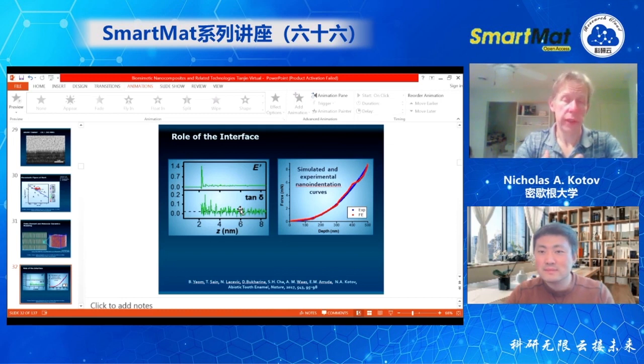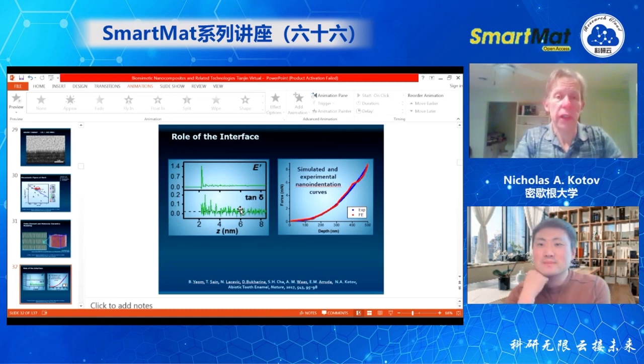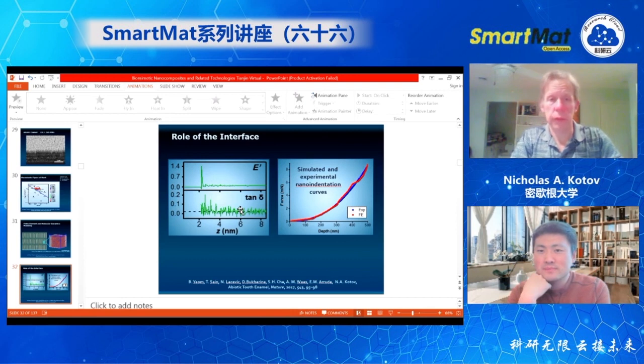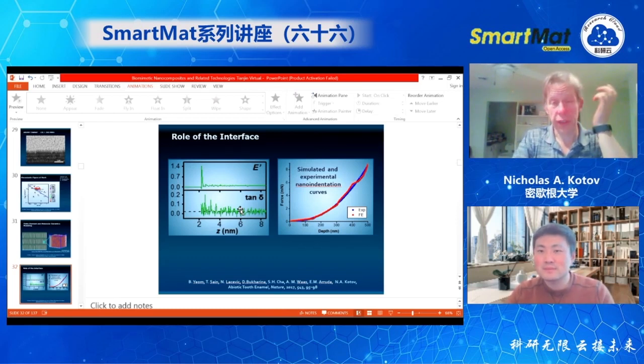So with that role of interfaces, you can compress, you can oscillate, but the entire material will respond. And that distribution of stress, that efficient distribution of stress as in enamel, it predicates the longevity of this material. So it turns out that the reason why enamel has such a structure is because many animals who have this columnar organization have one set of teeth for a very long time, say the elephants or humans.